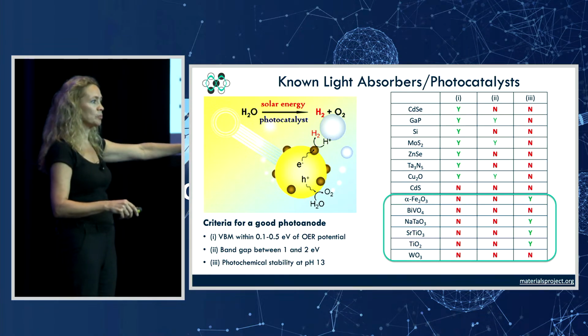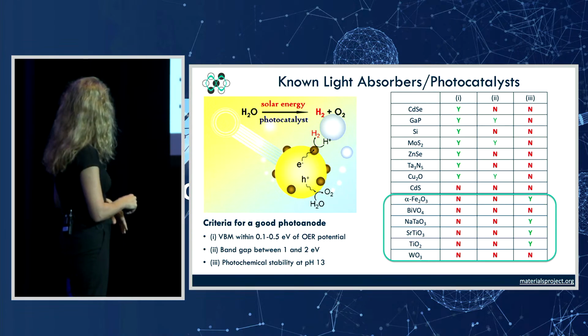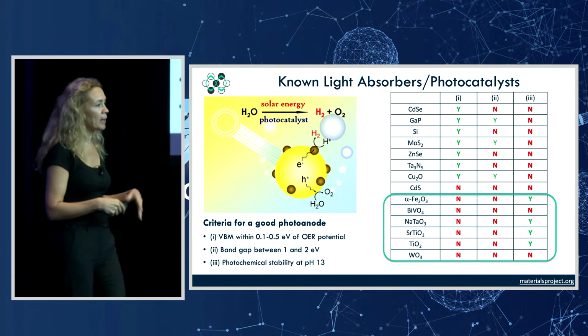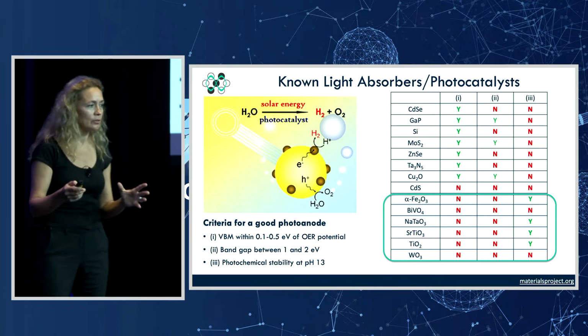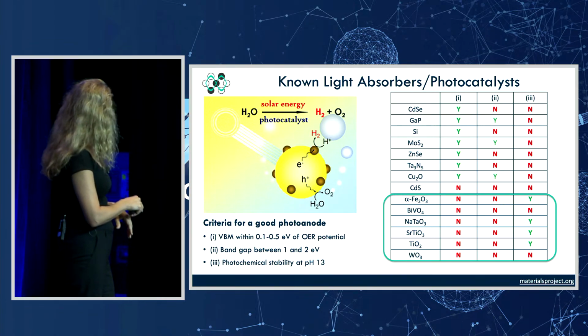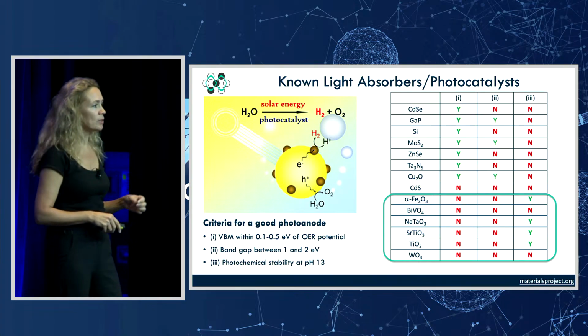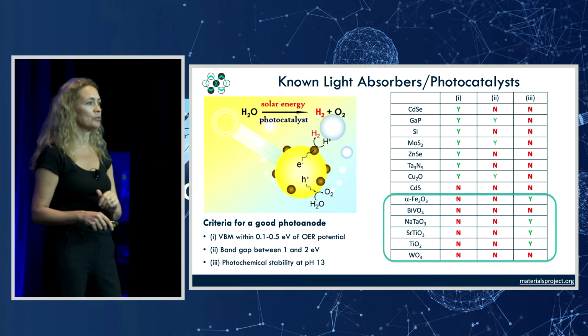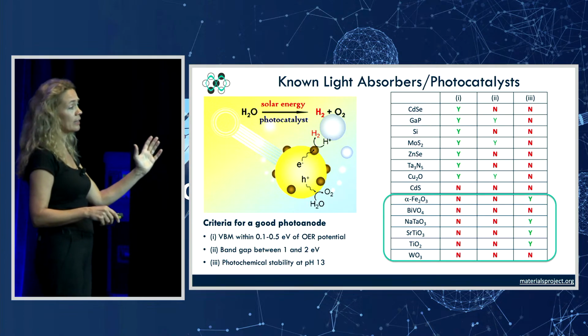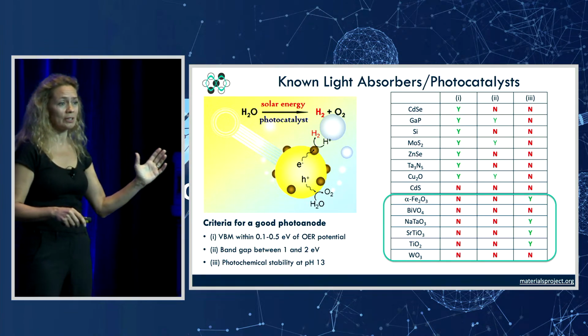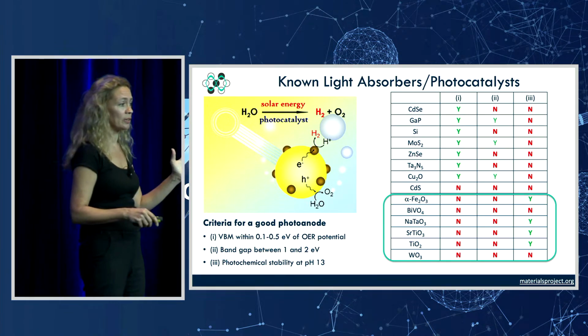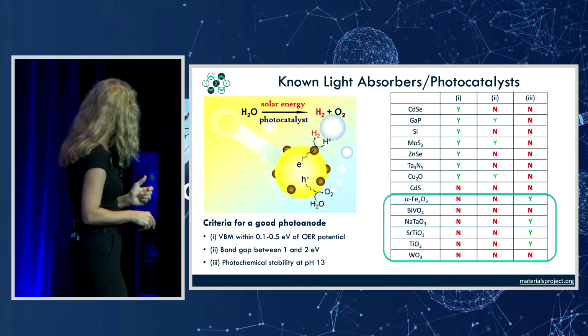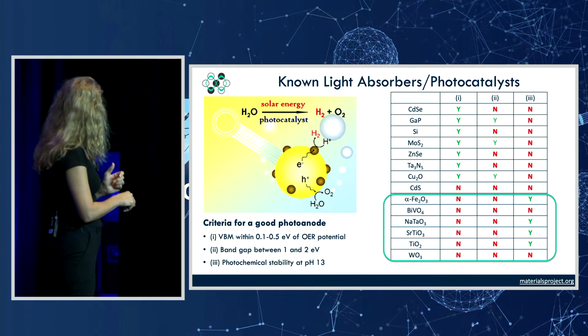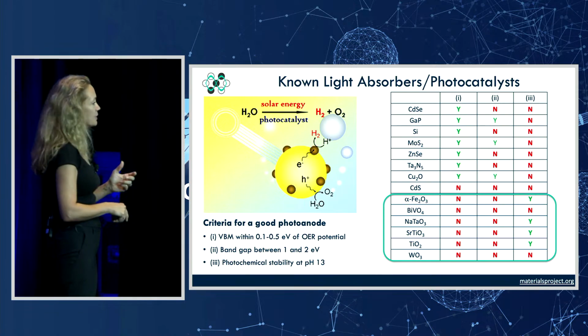The garden variety semiconductors that people have looked at did really, really well on criterion number 1. They just had a perfect, or a very good, position of the valence band maximum. They did okay on the band gap, but the last one was being stable under pH 13. We decided to go for the alkaline rather than the acidic side, because the acidic side is even worse. It's hard to find materials that are very stable under pH 1 or 0. So pH 13 was more benign, but still none of these guys were stable.